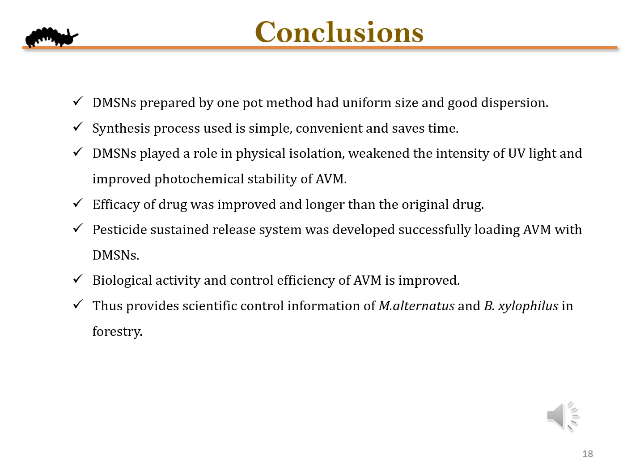Conclusions. From this paper, we conclude that DMSNs prepared by the one-pot method had uniform size and good dispersion. Thus, the synthesis process is simple, convenient, and saves time. DMSNs played a role in physical isolation, weakened the intensity of UV light, and improved the photochemical stability of AVM. Also, the efficacy of the drug was improved and is longer than the original drug. Biological activity and control efficiency of AVM is also improved.